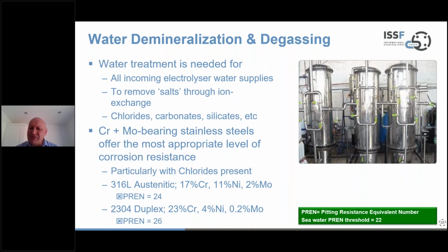And stainless steels lend themselves well to this type of process, particularly chromium plus molybdenum bearing stainless steels, because when you have chlorides present, you have a particular corrosion mechanism called pitting corrosion taking place. And for seawater, you can calculate based on the chemical analysis a pitting resistance number for each different chemical analysis of stainless steels. The threshold for seawater that's commonly referred to in normal ambient temperatures is 22. So any stainless steel with a figure above that will work well in these sorts of environments.